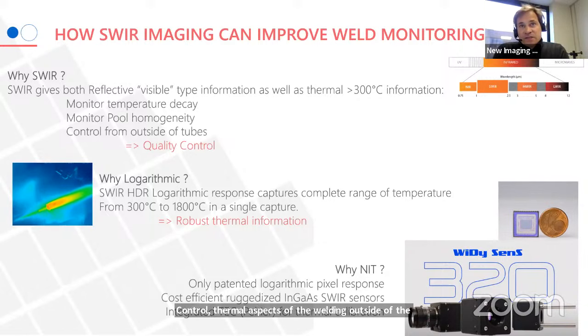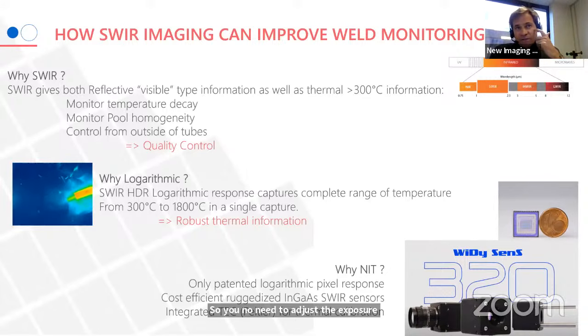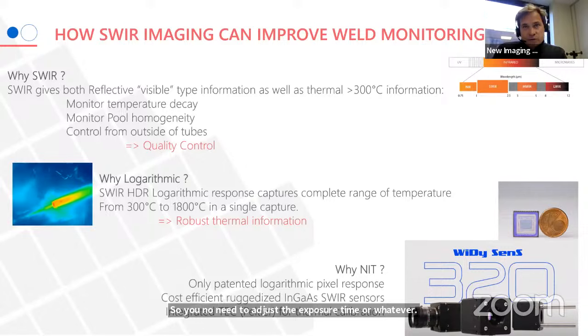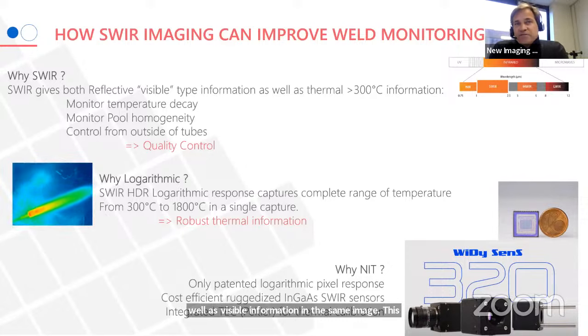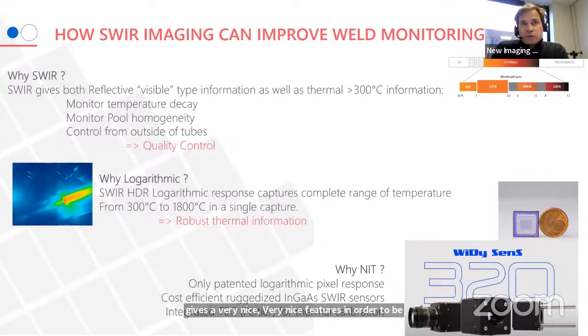Now, the second question is why logarithmic? The HDR logarithmic response captures a complete range of temperatures from 300 degrees to 1800 degrees in a single capture. So you don't need to adjust the exposure time or whatever. With a single exposure time, you can capture this complete range of temperatures. And so you have very robust thermal information as well as visible information in the same image. So this gives very nice features in order to be able to control your quality during the process itself.